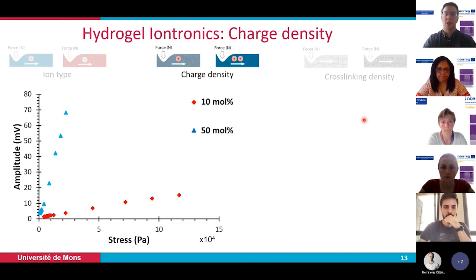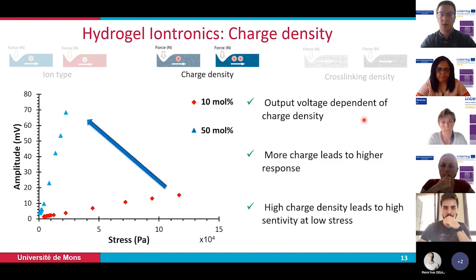Then if we look at the charge density, when we increase the charge density, we have a clear increase of the response. So we have an output voltage that's dependent on the charge density, and we have a higher response with more charge. And what is really interesting is that the high charge density materials have a really good sensitivity at low stress, at low pressure. So it's really interesting for applications.